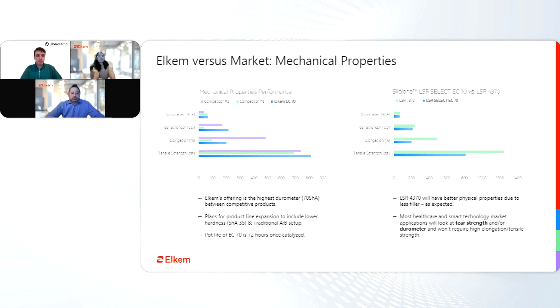So we've benchmarked our product against what is available currently, and this is how it's ranked. Our product is the highest in terms of durometer, 70 Shore A. Most of the physical properties, such as your tensile and tear, all outperform with a pot life of 72 hours upon catalyzation. Our elongation is relatively good for such a high hardness that's available on the market. There are current plans to develop a corresponding lower durometer hardness, ballparking at around 35 Shore A, to accommodate customers who want that lower hardness in the future.